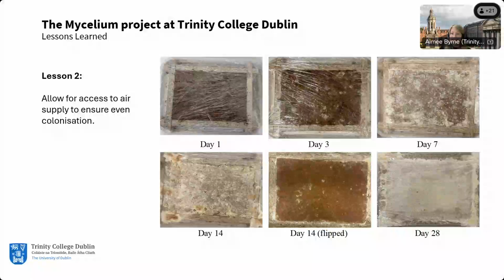The second lesson is that you have to allow for adequate airflow in these growing systems. They need oxygen, they need air to grow. And we found that initially we were just growing the white, we could see the white forming on one side, and then when we would demold, it was still brown sawdust on the other side, because that was originally covered by the mold that we had made. So we ended up then halfway through the process flipping our sample over and allowing the air to get to the other side a bit more.